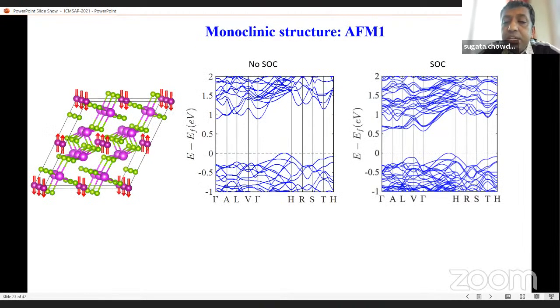Then he computed the band structure, including spin-orbit coupling and without spin-orbit coupling. If we don't include the relativistic effect, the band gap is different. On the other hand, if you use a full relativistic calculation, the band gap changes, and this is an indirect band gap. From there, we can conclude that the band gap, or electronic properties, can be affected by the relativistic effect or spin-orbit coupling.